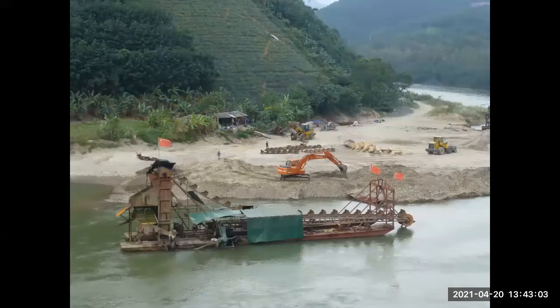These days, we're going further and further afield to source virgin rock and sand for concrete. The sand can't be weathered and rounded in the way beach and desert sands are. It needs to be angular to create a good structural matrix. And so it's surface mined from recent sedimentary deposits that lie beneath often delicate natural landscapes. Globally, it's acknowledged that we're about to simply run out of virgin angular sand. And so R&D for recycling our gigantic hard waste streams to produce both coarse and fine aggregate for concrete needs to ramp up urgently. And as it does, we building professionals need to promptly preference these recycled products via our concrete specifications.